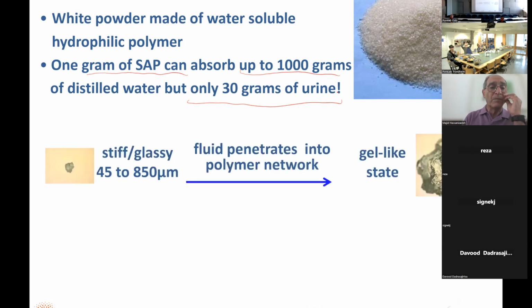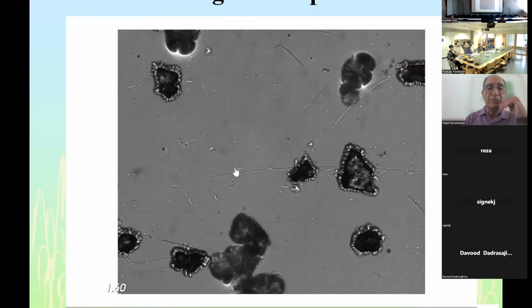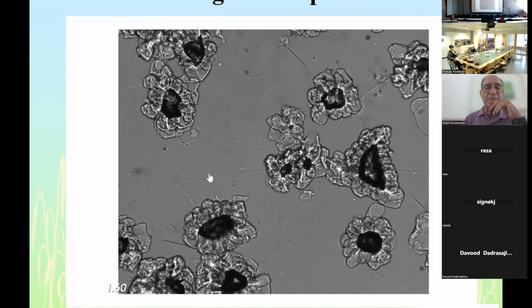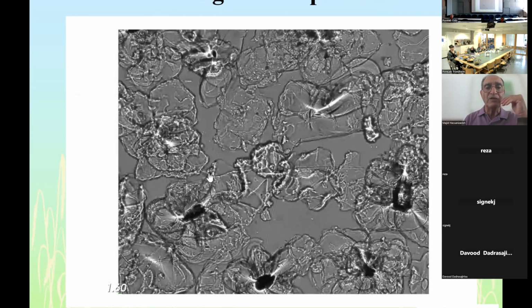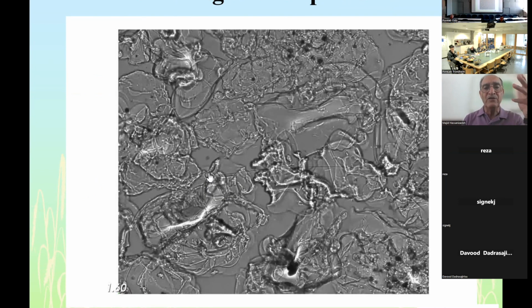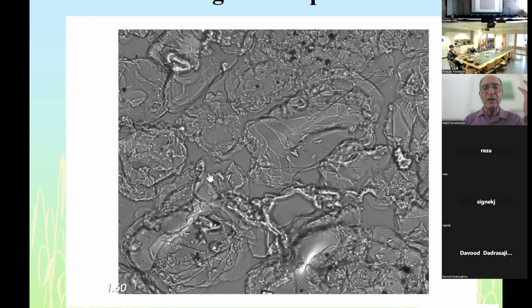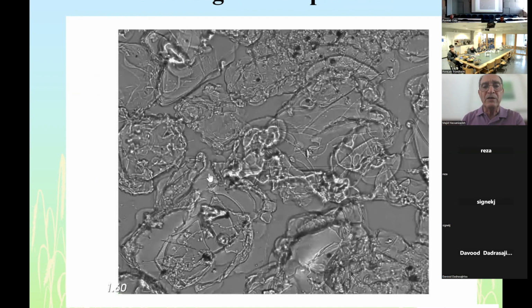So these are glassy, stiff particles, a few hundred microns in size. And then as the fluid enters, it becomes gel-like, basically becomes water when it absorbs so much water, but still keeps the shape of a solid material. You see that absorption of water happening here. We started with particles under the microscope, and this is real time. See, absorbed water becomes basically transparent.